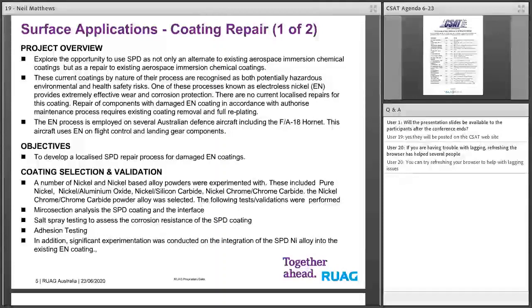It's quite a difficult process. So what we've done is that we've basically seen if we can actually deposit, blend out areas and actually deposit on the substrate, and more importantly to be able to get good bonding between our SPD deposition and electroless nickel deposition. We tried a number of nickel alloy based powders. We've come up with one which is performing quite well, and again, as we do always, we've put it through a number of significant tests and experimentation to make sure that it will meet the requirement. Next slide, please.